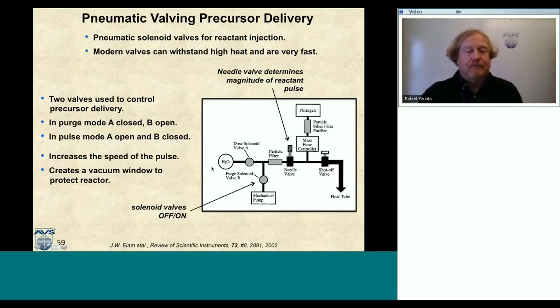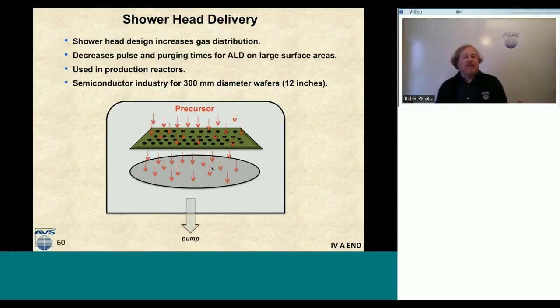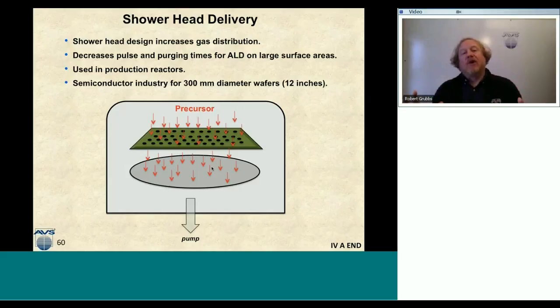Now, the last thing I want to mention is shower head delivery. I just mentioned this because it's used in the semiconductor industry to coat 12-inch wafers. So you've got to have your ALD precursor delivered across 12-inch wafers. And since time is money, we really want to get that distributed very quickly to decrease the pulse and purging times as we're doing these ALD chemistries on large surfaces. And this is just used in production reactors. And since the semiconductor industry has moved to these 300 millimeter wafers, these 12-inch wafers, and time is money, we want to make sure that our pulses and our purging times for ALD deposition processes are as fast as possible.